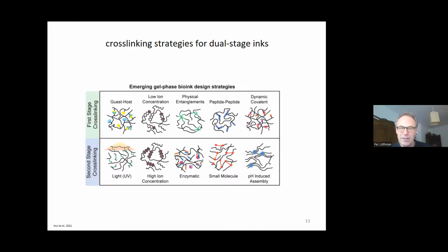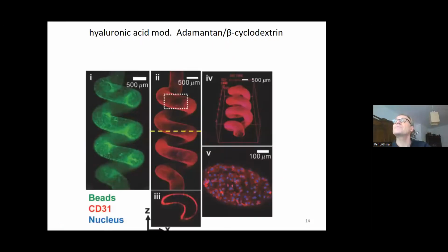And you see, there are two things that we need for the bioink. It must be printable, but it also has to contain components that make the construct, the printed organ, stable post-printing. So here is one example. This is hyaluronic acid modified with adamantane beta cyclodextrin, and this is a dual stage cross-linked bioprinted structure.